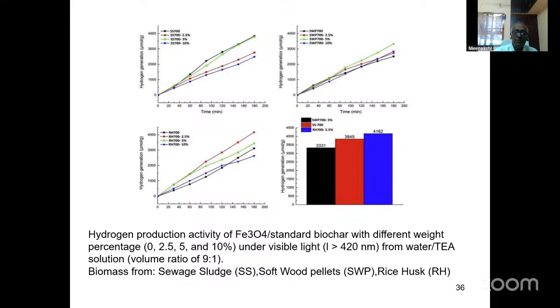Actually, they used three biochars. One biochar from sewage sludge, another biochar from softwood pellets, another from rice husk. So this is sewage sludge, this is softwood pellet, and this is from rice husk. They found different hydrogen evolution reactions for each. They found that this one, actually this 2.5%, is found to be most efficient. Here you can see hydrogen evolution.